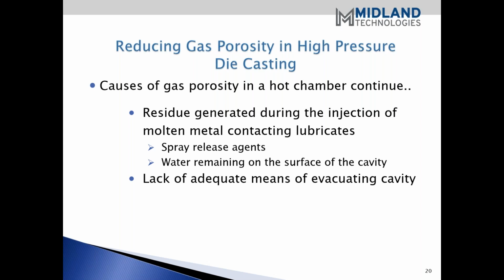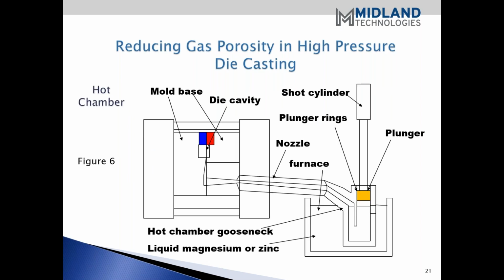So causes of gas porosity in the hot chamber: the residue generated during injection of the metal coming in contact with lubricants, same thing as we have in the cold chamber. The spray, the water remaining on the surface, and again the lack of adequate evacuation. Next slide. This is just a cross-section area. But you can see the problems that occur with the amount of air present prior to injecting the metal. You have to evacuate a portion of the gooseneck, the nozzle, and the spreader, and of course the cavity.